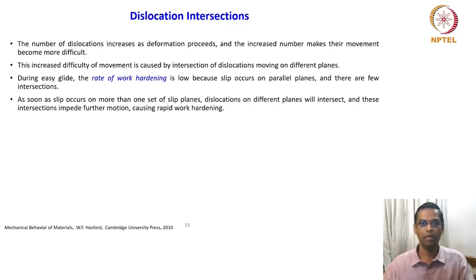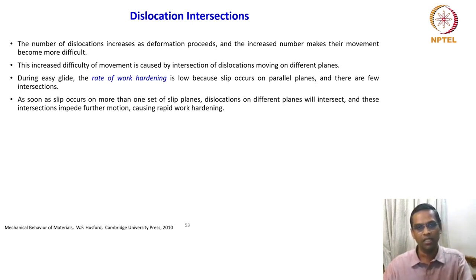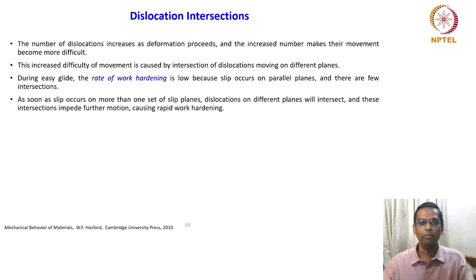When talking about multiple slip — where several slip planes are activated — all the slip planes will move in different directions depending upon the easy glide orientation. Once additional slip planes are activated, dislocation motion takes place in all the randomly oriented planes, and one would expect these dislocations to interact with each other and impede motion. That is where restriction comes into play, which is an indication of work hardening.